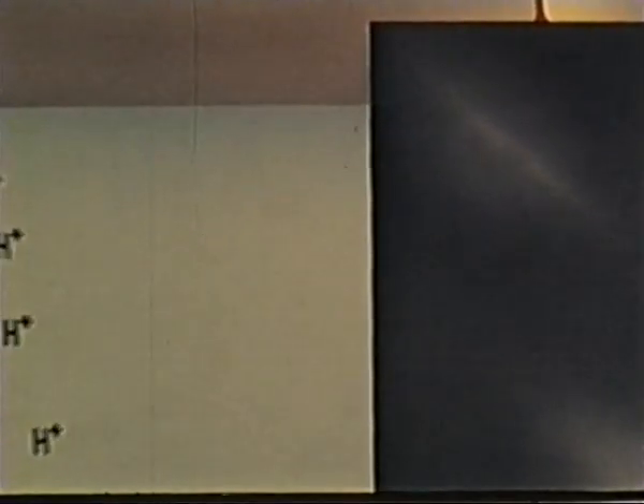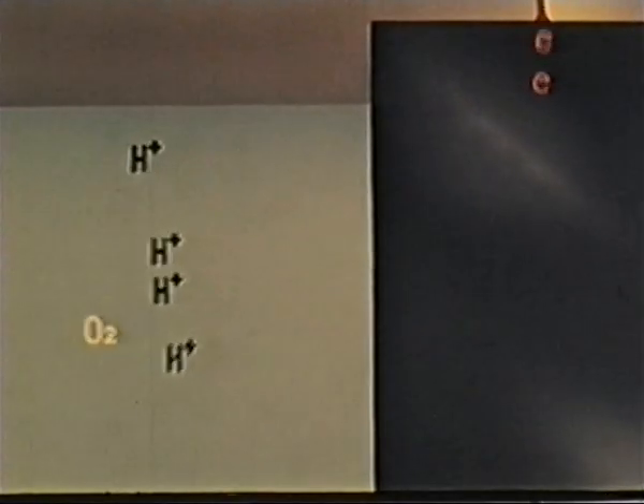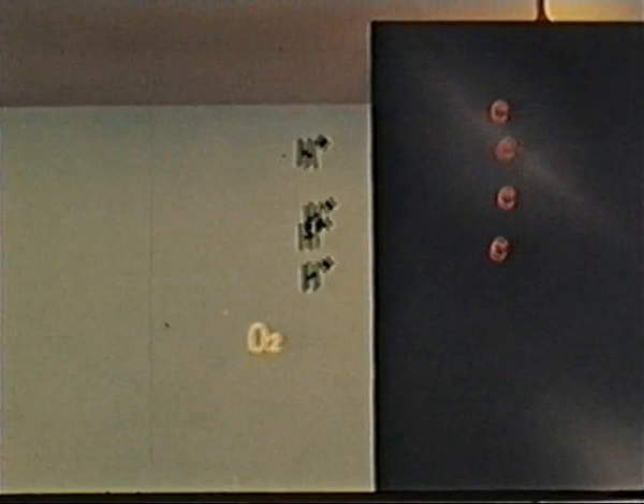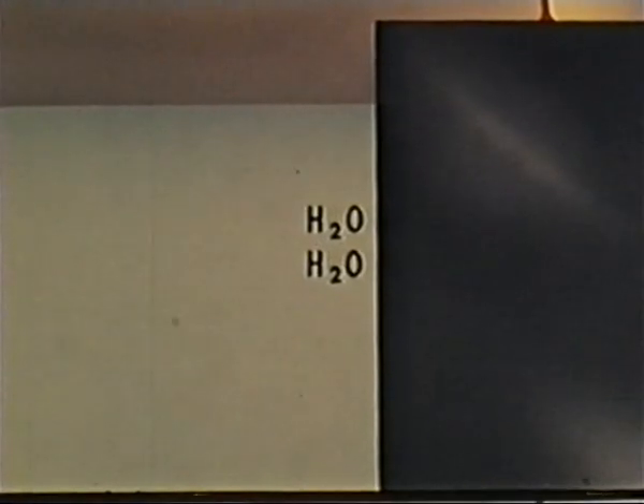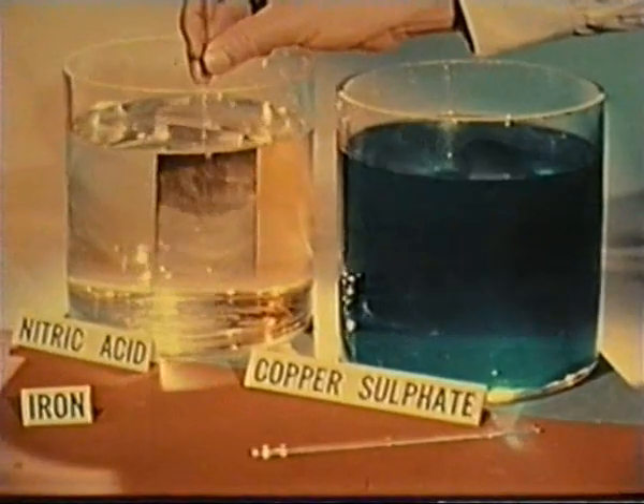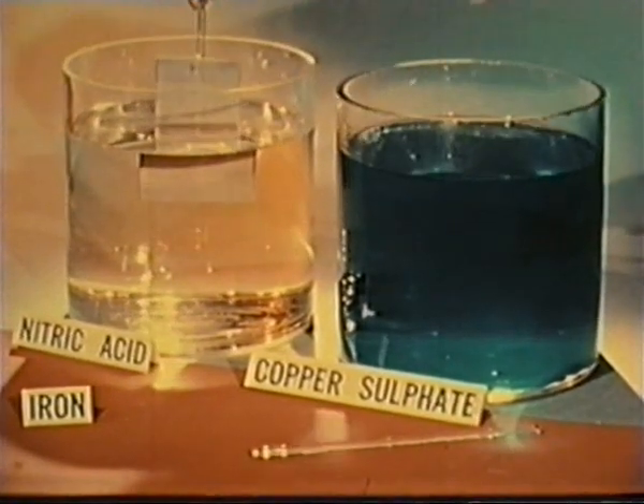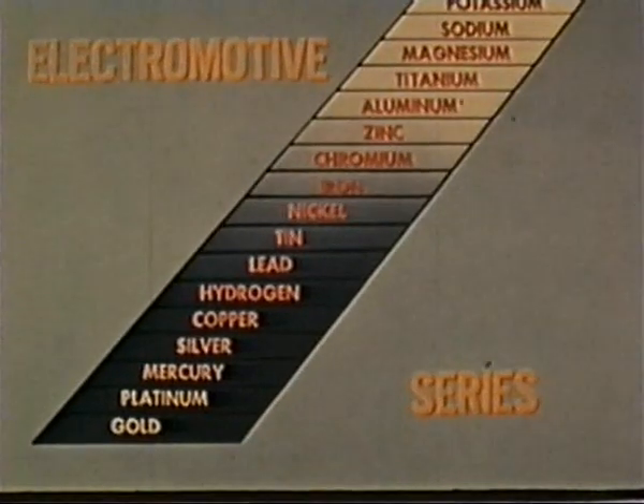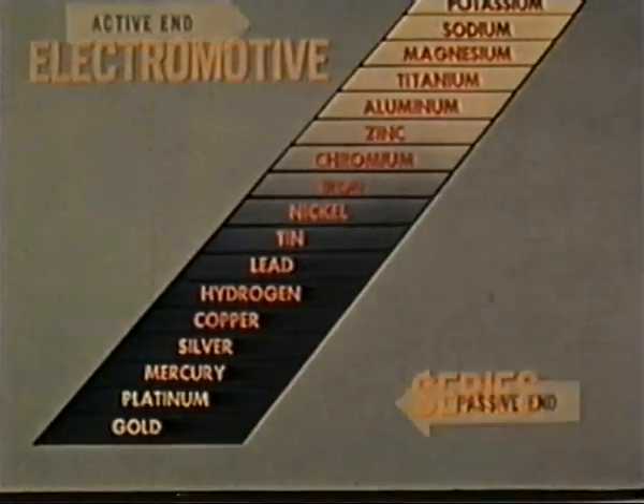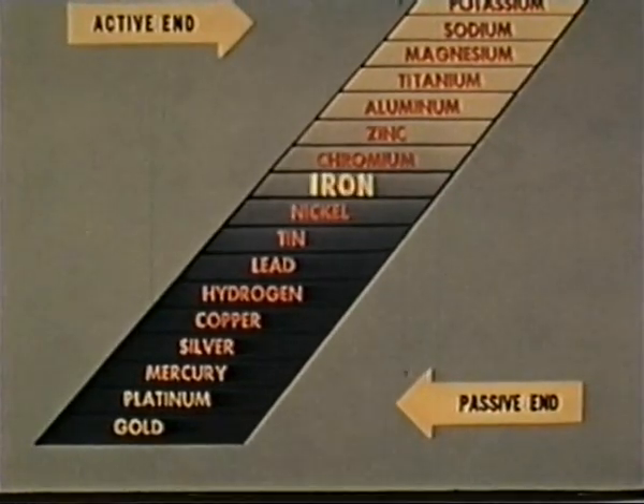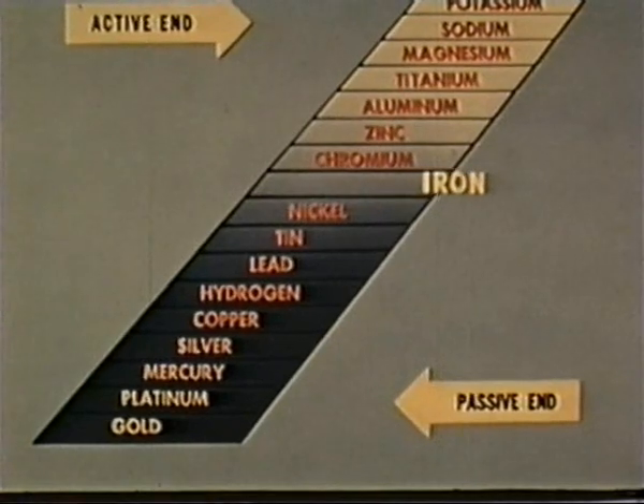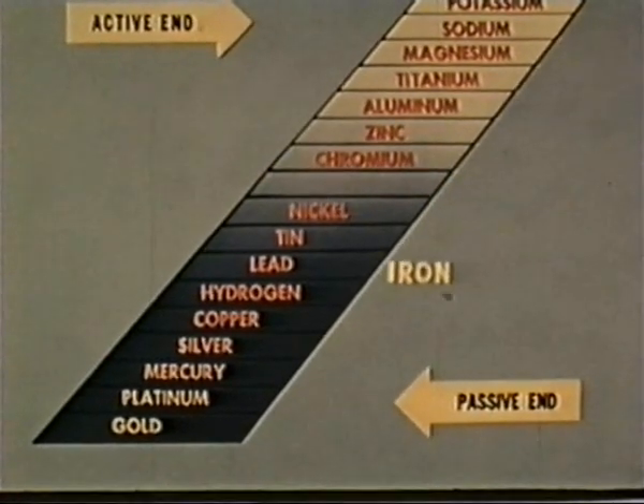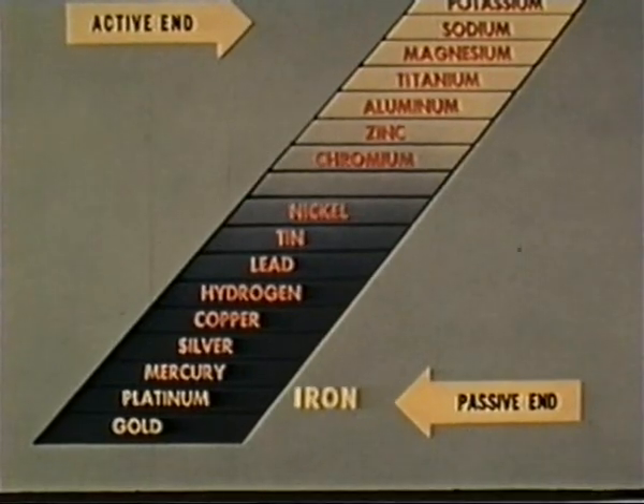The effect of oxygen on corrosion is variable and complex. We can see that it increases corrosion by acting as an electron acceptor and removing the film of hydrogen at a cathode. In higher concentrations, oxygen can also retard corrosion. Oxygen or oxidizing agents such as nitric acid can form invisible protective films of their own and in this manner reduce corrosive action. The metal is said to have been rendered passive. When some active metals become passive, they take on many features of the noble metals. For instance, iron made passive by an oxygen layer or oxide film approaches the noble potential of platinum and resists corrosion. This fact is easily demonstrated.